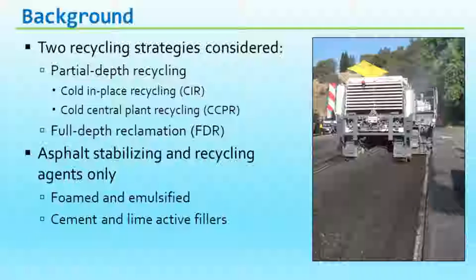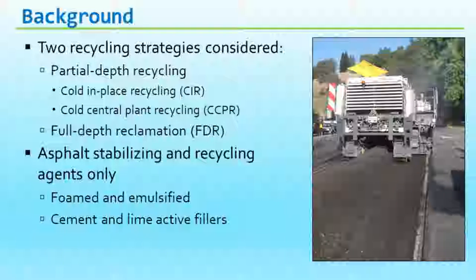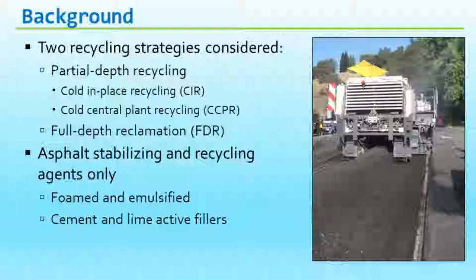In terms of the study, you're looking at two recycling strategies. So again, what we're calling partial depth reclaim materials and full depth reclaim materials, with the partial depth being cold in place recycling and cold central plant recycling. The study, by the terms of reference, was limited to asphalt stabilizing materials only. So if we're stabilizing with cement only, that is not included in the study, and we were expressly told not to include it. So we're looking at both foamed and emulsified asphalt, and then looking at cement and lime as the active fillers. There are a lot of other active fillers being used out there, but in fairly small quantities. So we restricted the study with the approval of the panel to look at just lime and cement.